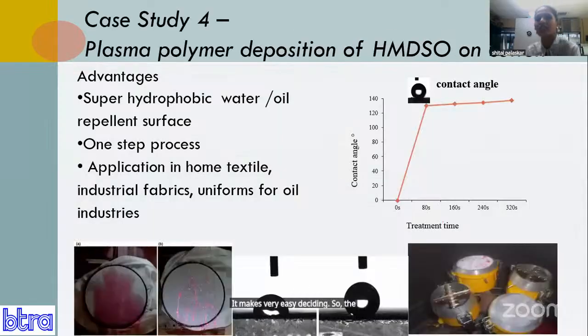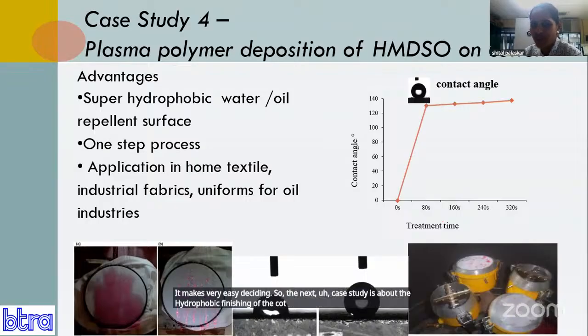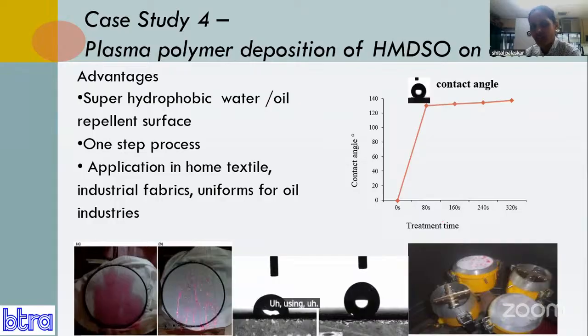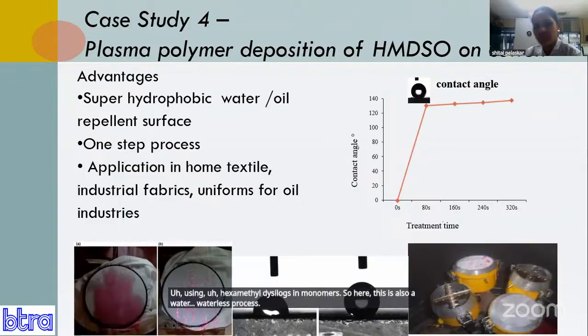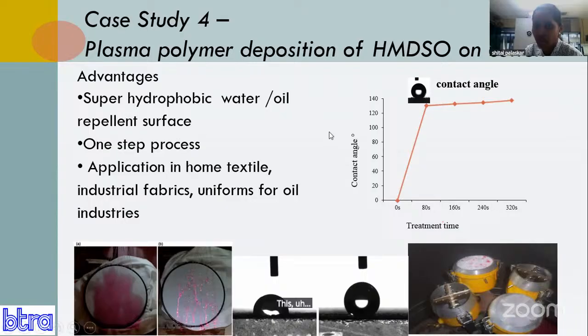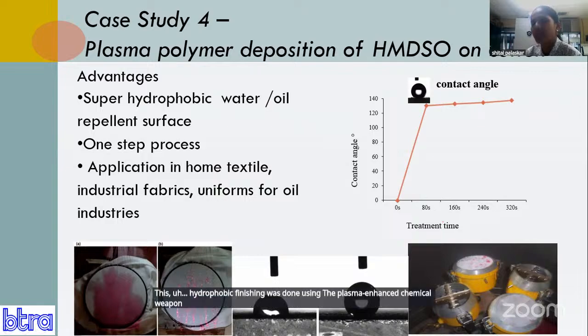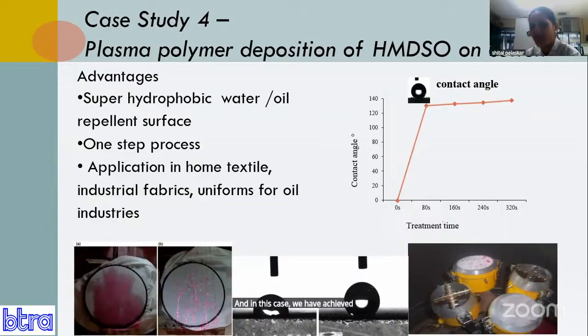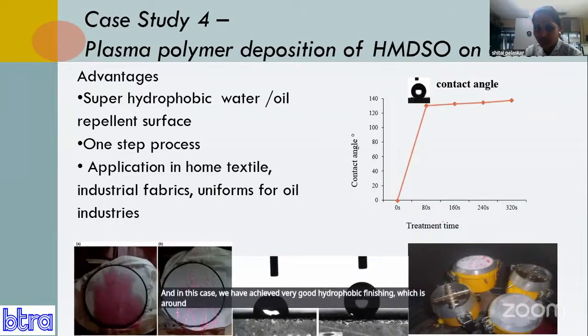The next case study is about the hydrophobic finishing of cotton fabric using hexamethyl disiloxane monomer. This is also a waterless process. This hydrophobic finishing was done using the plasma enhanced chemical vapor deposition process, where only a small amount of monomer was used. The monomer used was HMDSO, that is hexamethyl disiloxane. In this case, we have achieved very good hydrophobic finishing, with around a 135 degree contact angle.